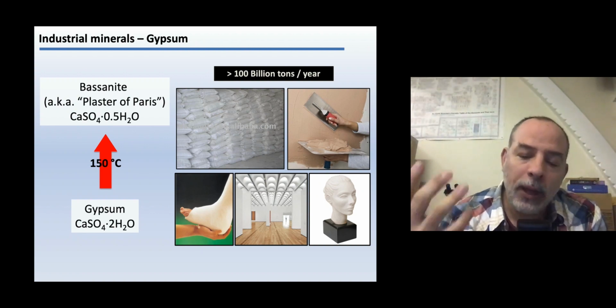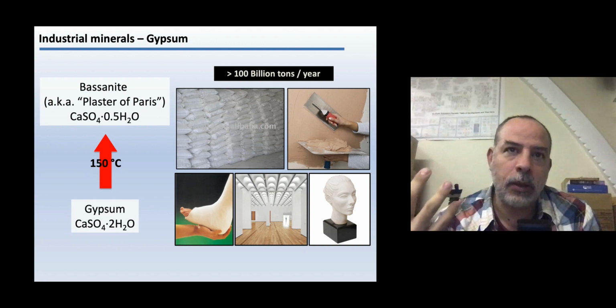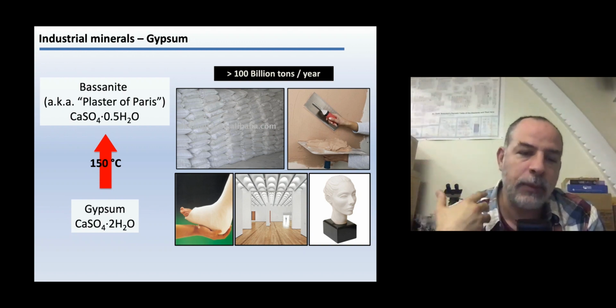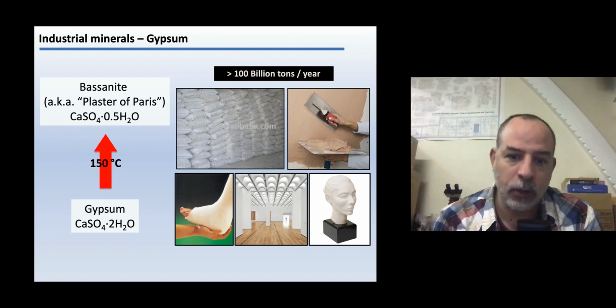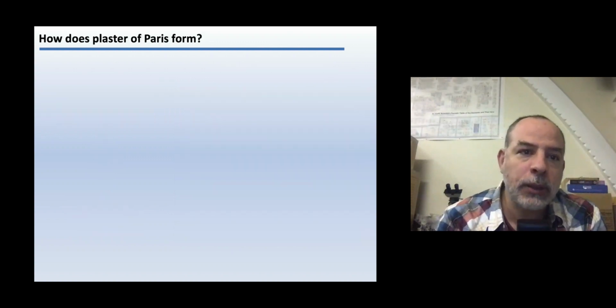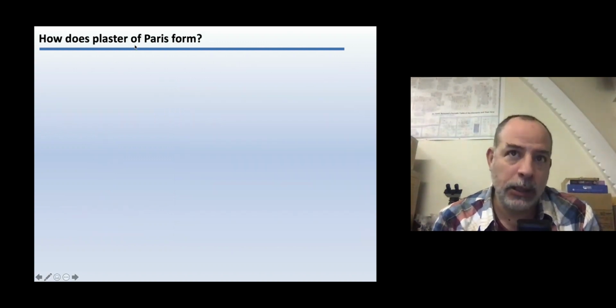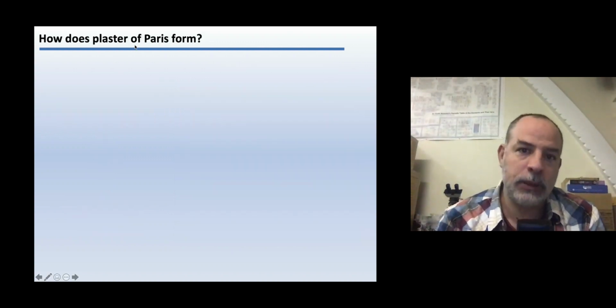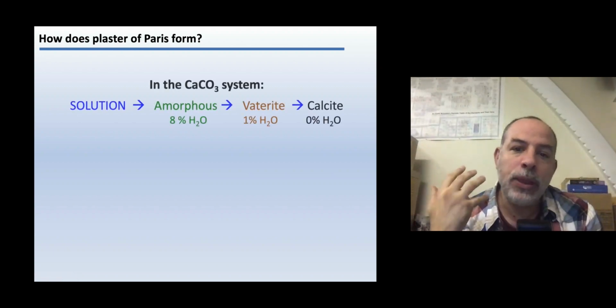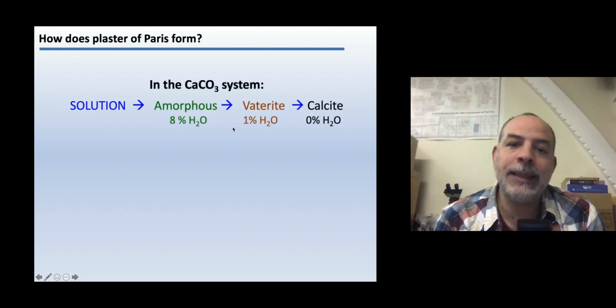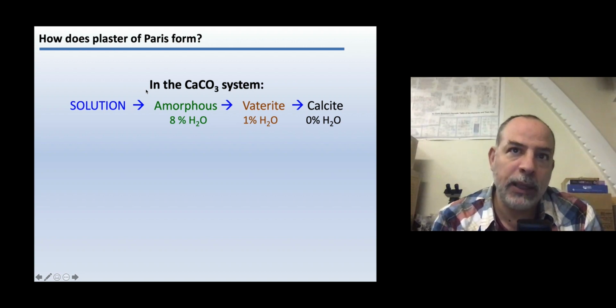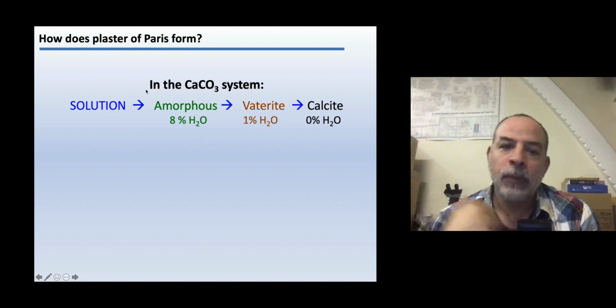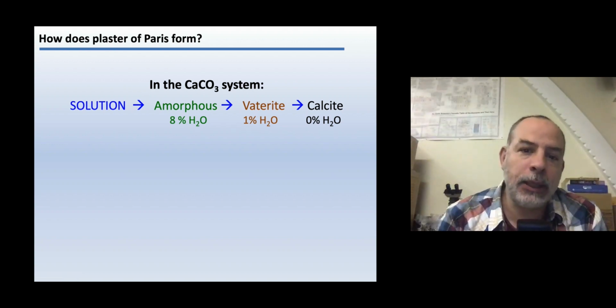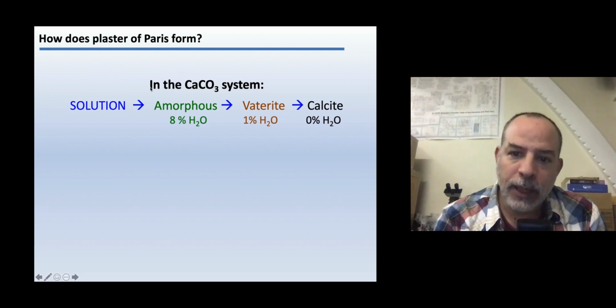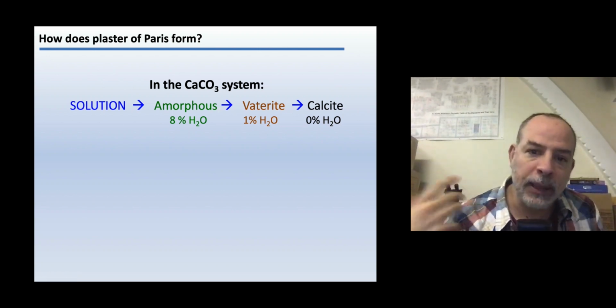Okay, so one of the research that was very fruitful a few years ago, it was a very nice collaboration with people from different universities, was to try to understand how plaster of Paris or bassanite forms. Initially we thought that this crystallization pathway of plaster of Paris was going to be similar to the crystallization pathway in the calcium carbonate system, in which we go from solution to an amorphous phase to vaterite and then calcite via dehydration.